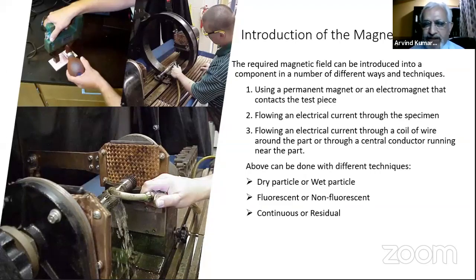Now when this was seen, you cannot accept this. I said, no, this is not the way you're doing. Then it was like, they've been doing this for so many years. So I said, you get a Gauss meter and check. Once you remove the field, you check what is the magnetism. And with the Gauss meter, it is showing 0.1, 0.2 reading, nearly zero. And when the part is not magnetized, whatever amount of dry powder or wet powder you apply, it is not going to form any indication. So mostly you should ask for a continuous method of magnetization. And if somebody is doing residual, you have to be careful and make sure that the residual method is appropriately being done.